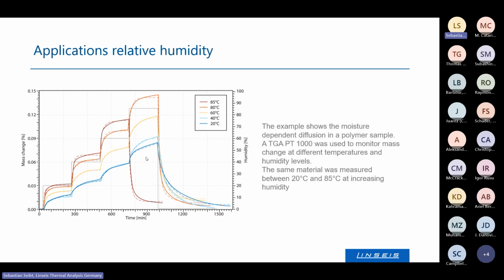This is a test we did by ourselves. We tried to redo what our customers were doing. They can also do that under different pressure levels. And doing this proves that polymers take up humidity out of the air. Depending on if it's high density, low density, what's the surface structure, this influence is dependent on the humidity level, and it's also dependent on the temperature level.